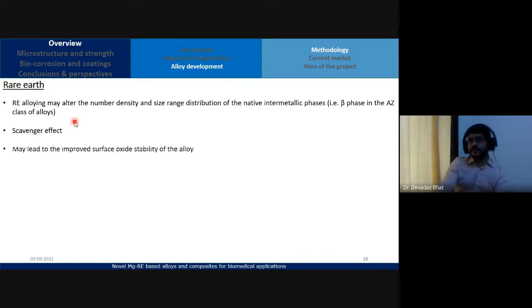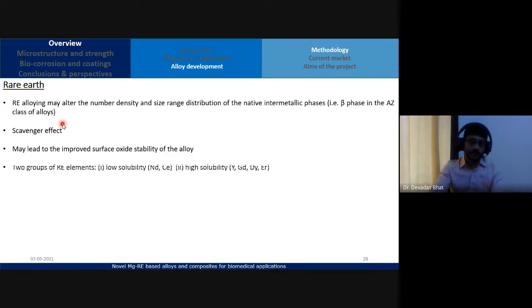Again, why rare earth? Because it will lead to improved stability, the surface oxide stability of the alloy. We are going to classify the rare earth elements into two groups. One is the low solubility group, which is neodymium and cerium. Then we have the high solubility group, that's yttrium, gadolinium, dysprosium, erbium, and so on. In our case, we have taken erbium here.